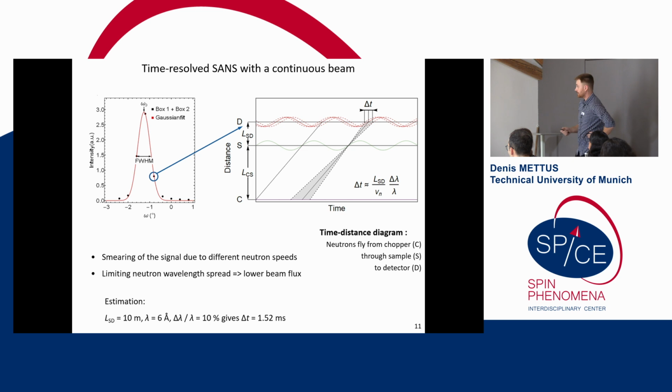One last practical thing is that we don't actually measure the rocking curve simultaneously. It's important to remember that we measure each point separately for the rocking curve. So we fix the angle and we measure the intensity as a function of time and then reconstruct the rocking curve. This doesn't change the physics behind the subject, but it's very important to remember because there are a lot of underwater stones and artifacts you can hit when you do your experiment.